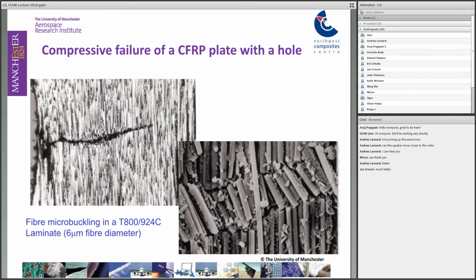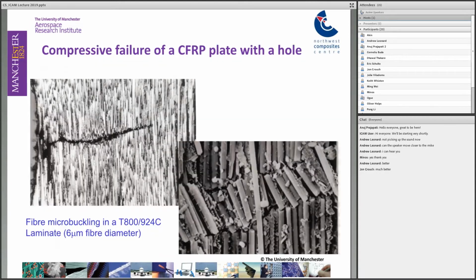But of course, that image has failed to identify, on the left-hand side of the hole under those delaminations, a critical damage mode in the form of fiber microbuckling that we cannot see and we have failed to detect. Here we can see on the left-hand side an optical micrograph where there's a thin crack growing across the width of the laminate from the edge of the hole. And it looks like a fatigue crack in metals under tension. But this one is not under tension, it's under compressive loading.